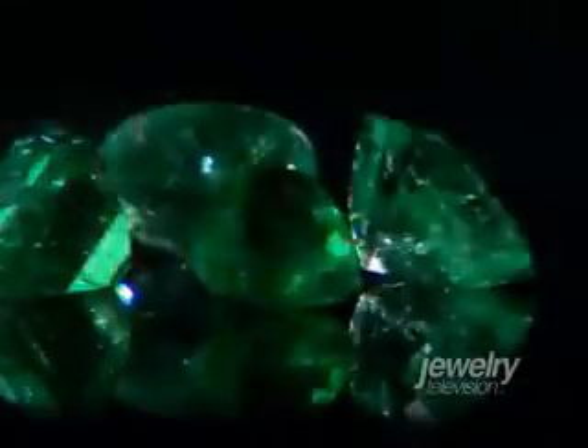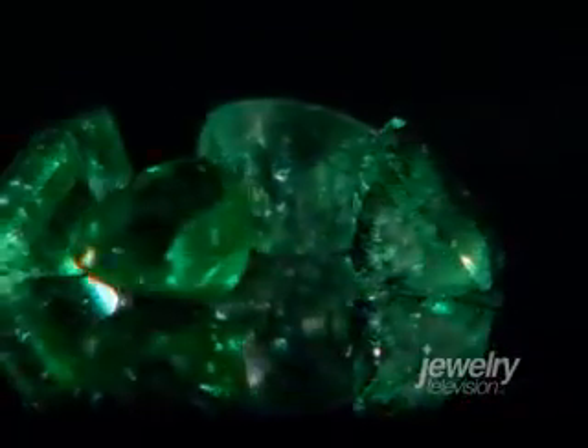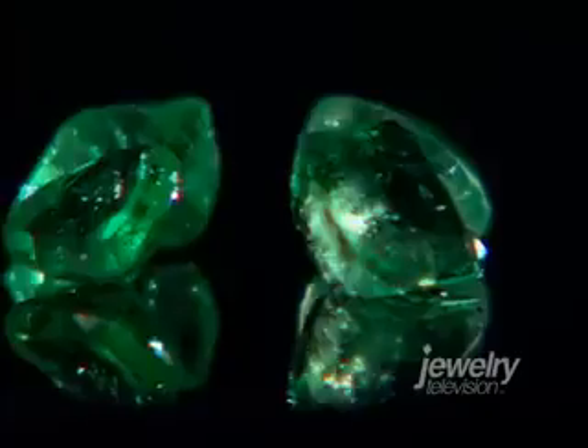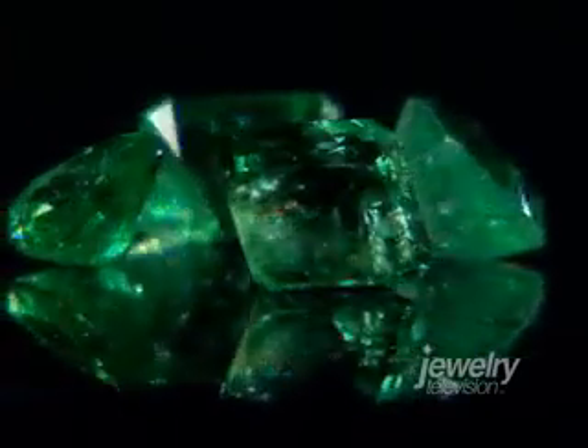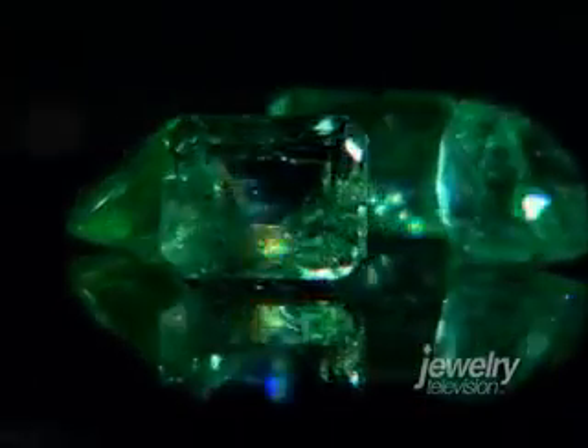After gemstones are cut, they are often treated to enhance their natural character and beauty. Emeralds are typically treated with an oil or resin to fill fractures and hide surface imperfections. Emeralds are routinely oiled to enhance their beauty. It's not improving their color, it's improving the clarity. And this is going back to the times of Cleopatra. It's actually noted that emeralds were oiled to make them more beautiful. So it is a very standard routine practice for emeralds.